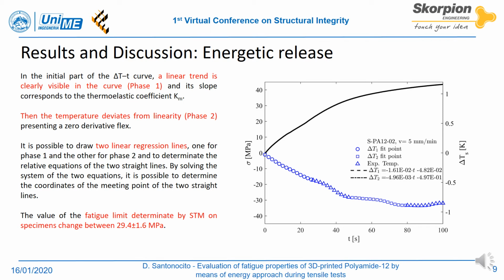During static tensile tests, the evolution of the specimen's surface temperature has been evaluated by means of an infrared camera. The applied stress is reported versus the specimen's surface temperature variation, estimated as the difference between the instantaneous temperature and the initial temperature of the surface recorded at time 0. The temperature data has been filtered with the Hampel filter, with a data span of 10%, in order to reduce the outliers and highlight the thermoelastic trend.